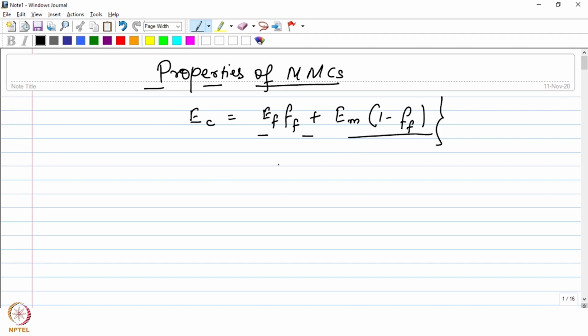And we have also defined the minimum and the critical fiber content for any strengthening benefit to occur in the composite material. So although the rule of mixtures generally gives you a higher value for the particular property that you are looking at, nevertheless, this gives you a first-hand approximation of the property of any composite material.